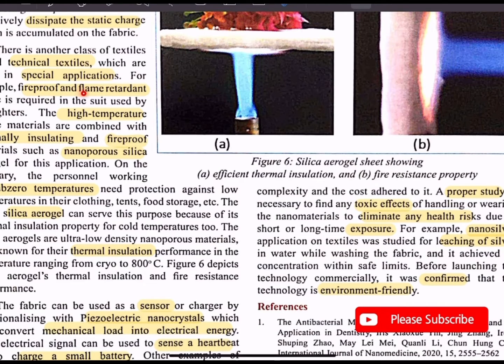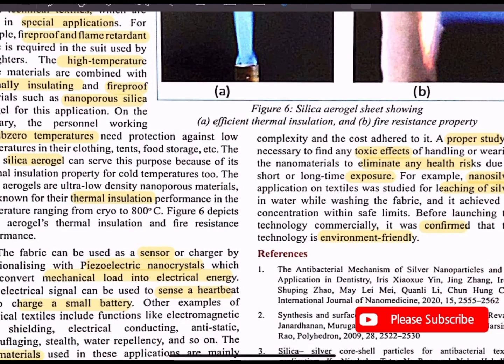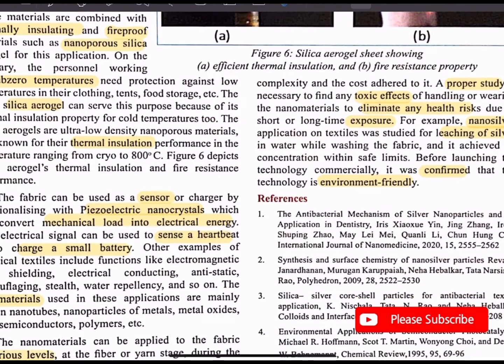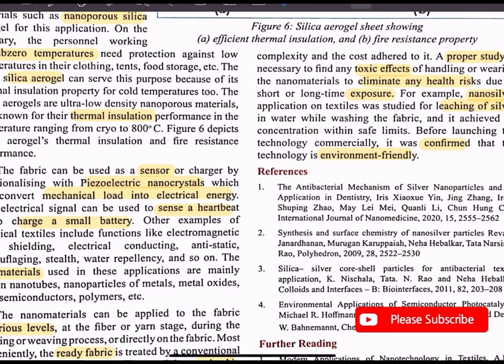For example, fireproof and flame retardant fabric is required in the suit used by firefighters. The high temperature stable materials are combined with thermally insulating and fireproof materials such as nanoporous silica aerogel for this application. On the contrary, the personnel working at sub-zero temperature need protection against low temperature in their clothing, tent, food storage, etc. The same silica aerogel can serve this purpose because of its thermal insulation property for cold temperatures too. The silica aerogels are ultra low density nanoporous material best known for their thermal insulation performance in the temperature ranging from cryo to 800 degrees Celsius. Silica aerogel's thermal insulation and fire resistance performance.